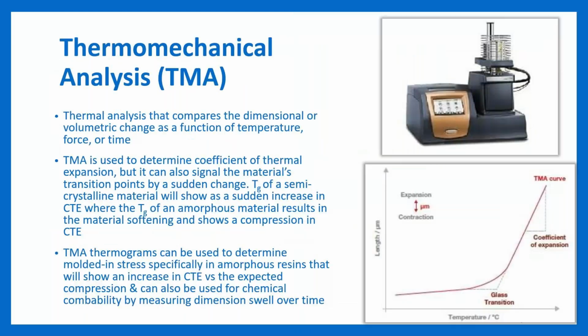Okay. Thermomechanical analysis, TMA. And so this is a thermal analysis that's going to compare dimensional or volumetric change as a function of temperature, force, or time. Generally, it's per temperature because they use this test most commonly to determine your coefficient of thermal expansion, so CTE, of your materials. What's nice about it is not only will you determine that across the range, but you can also use it to determine then your transition points.